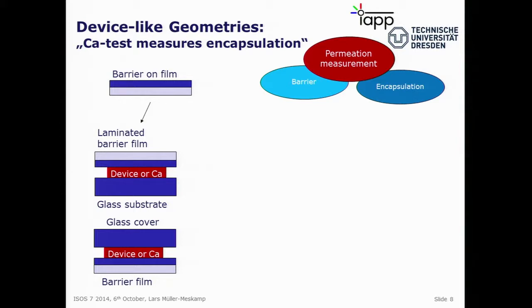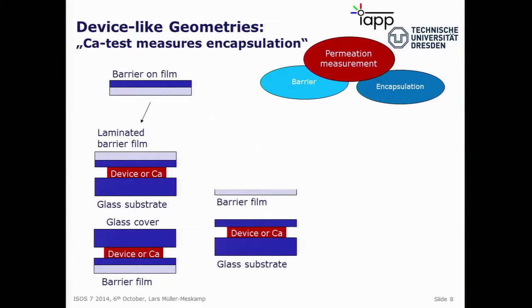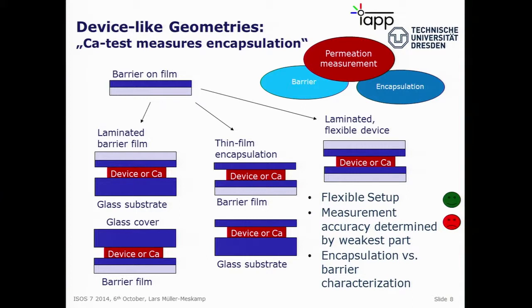So you can imagine this is a device or a calcium test. And you can do many other things, so you can use thin film encapsulation, so you put your calcium below the thin encapsulation layer, or you use glass on the back. And of course, this influences what you are measuring. So you have a very flexible setup, but you have to be very careful because the measurement is always determined by the weakest part. If you don't have a good side encapsulation, or if one barrier is much weaker than the other one, then you're measuring the weaker one and not the good one, which you might want to measure.